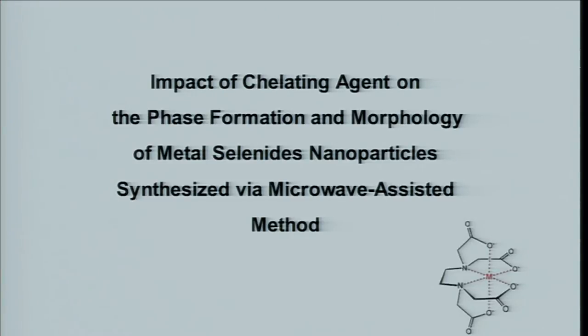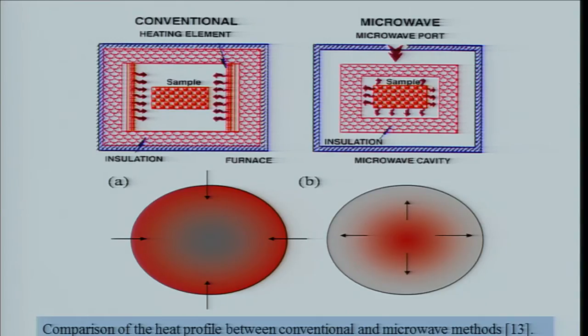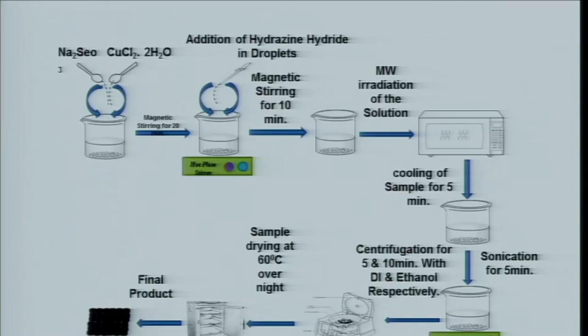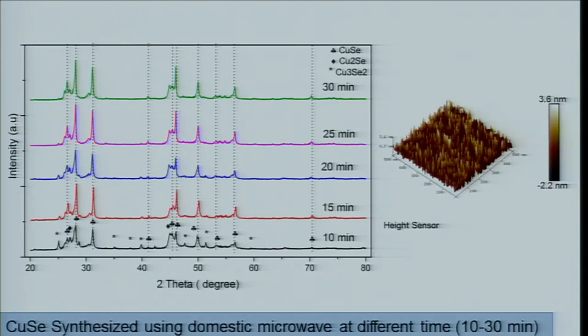So we have used a microwave approach for this particular endeavor. With a microwave-assisted method, you can have more volumetric heating, more uniform heating, more controlled heating. And this is the kind of setup that we have right now. But the thing is, we just have a domestic microwave that we bought for 200 ringgit, I think 250 ringgit. But again, with this kind of arrangement, we were able to get the synthesis complete in less than 15 minutes, whereas the other approaches I mentioned took quite a long time.